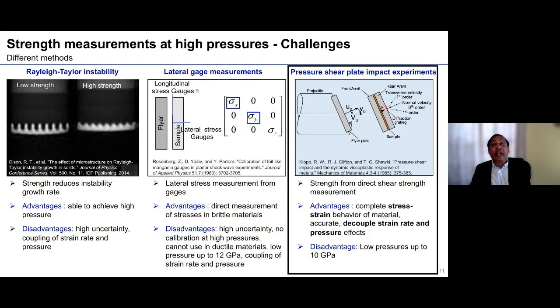Another popular technique is using lateral gauges. As I mentioned, normally from the free surface velocity measurements we can obtain the normal stress in the direction of the compression, but the lateral stress we don't know. But one can employ lateral stress gauges, such as manganin gauges, to measure the stress.